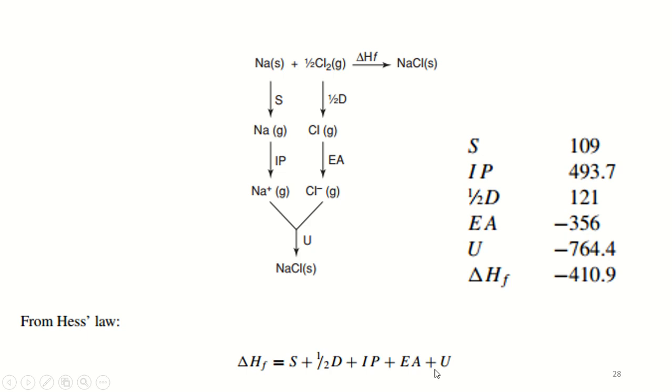So an early application was the calculation of electron affinities, for which the data were not then available. The stability of an unknown compound may be estimated. It is necessary to assume a structure in order to calculate U. Although there are obviously errors involved in choosing r_e, these are usually unimportant compared with the effect of some of the other energy terms in this equation.